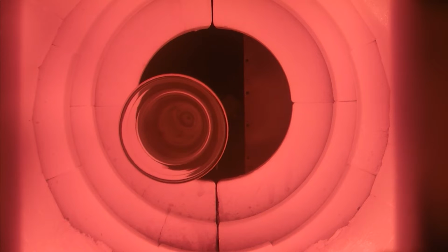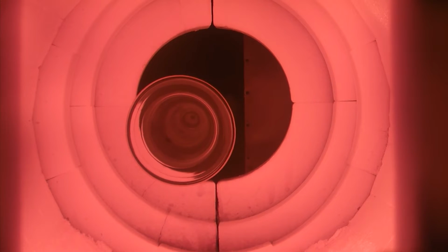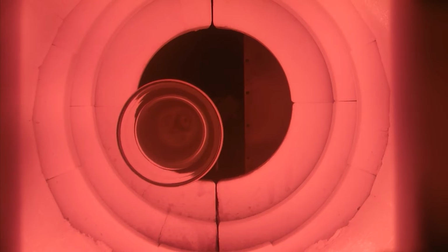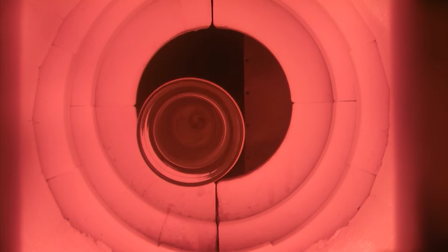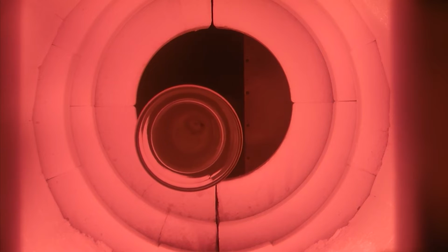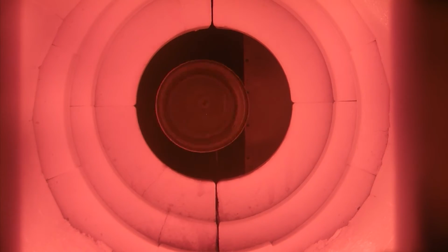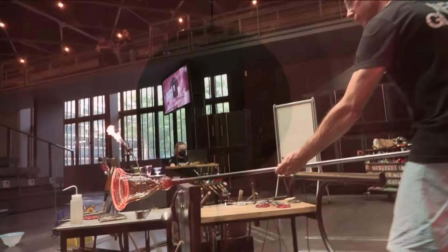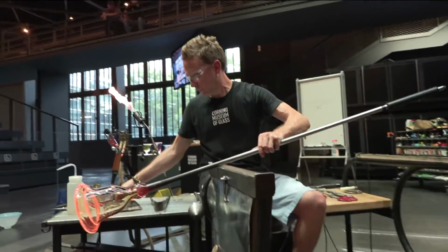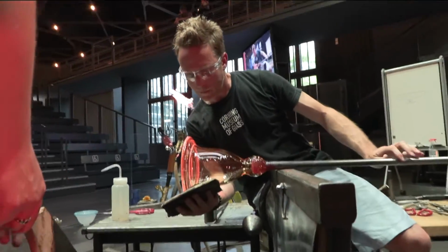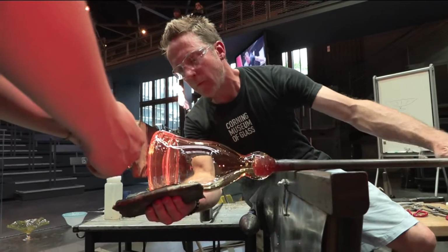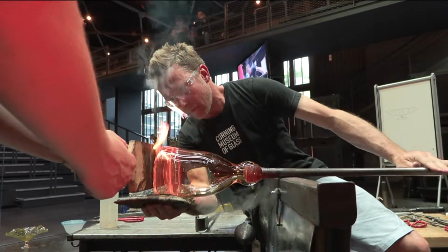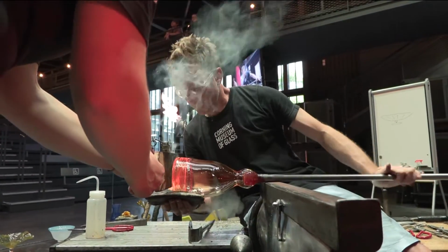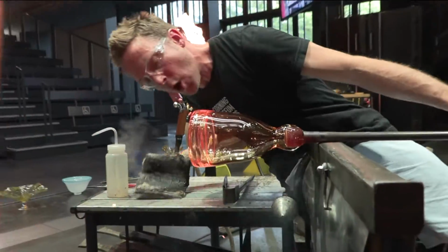Then after that, once you blow the glass out, it becomes thinner, and the thinner the glass is, the more quickly it dissipates its heat. It has more surface area exposed, and it lets off its heat a lot faster. So right now, maybe he's got like 30 seconds or so to work with the glass before he needs a reheat. Once it gets on the punty, once it's flipped around, maybe 20 seconds. So he's got to work very quickly.